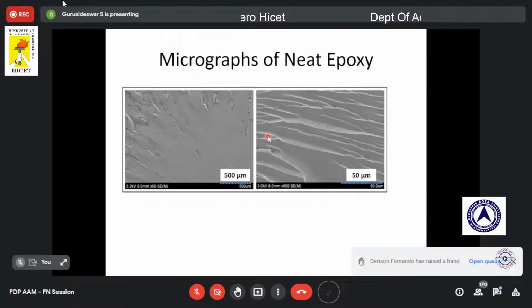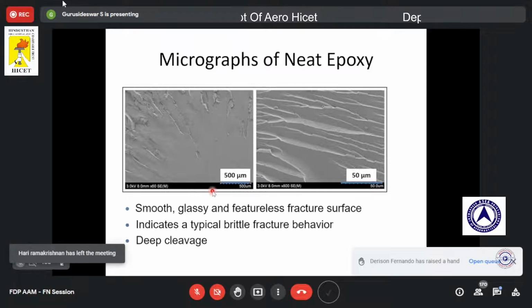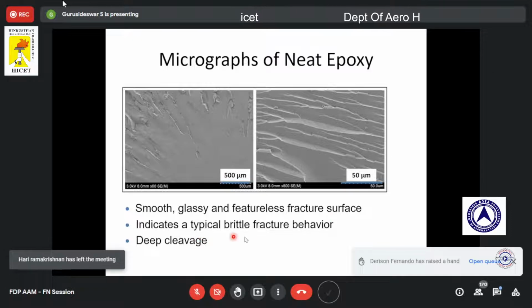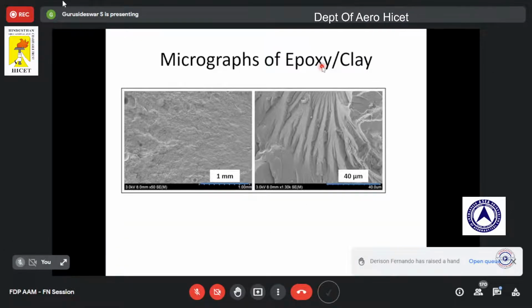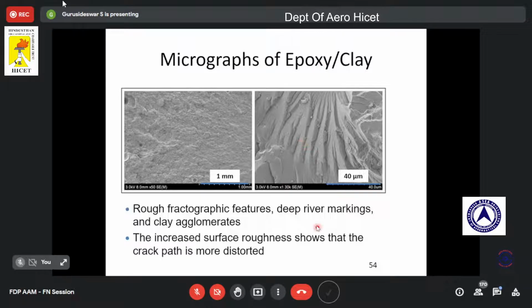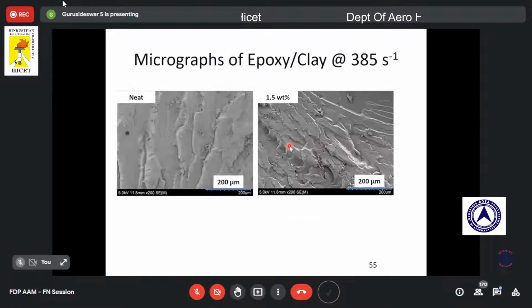Yeah. So now let me quickly come to the end of my talk. This figure shows the micrograph of neat epoxy at different magnification. You can see a smooth, glassy, featureless fracture surface, which indicates typical brittle fracture behavior. And in clay epoxy, we can see there is agglomeration and deep river markings, and also the surface roughness is increased, which confirms the clay particles. And again, this is the figure of clay epoxy at higher strain rate.